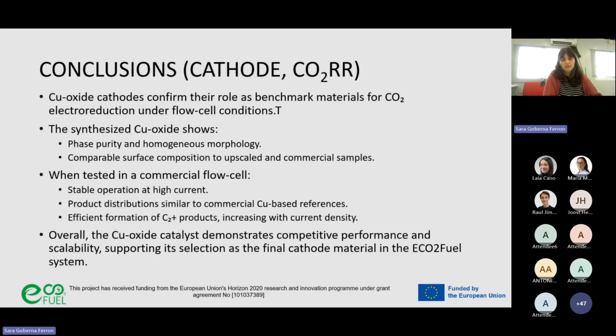So as conclusions for the cathode, copper oxide cathodes confirm their role as a benchmark material for the CO₂ electroreduction. Our synthesized copper oxide shows phase purity, homogeneous morphology, and comparable surface composition to the upscaled and the commercial samples. When we tested in a commercial flow cell, we observed stable operation at high current, product distribution similar to the commercial copper oxide reference, and the efficient formation of C2 plus products that increase when we increase the current density.